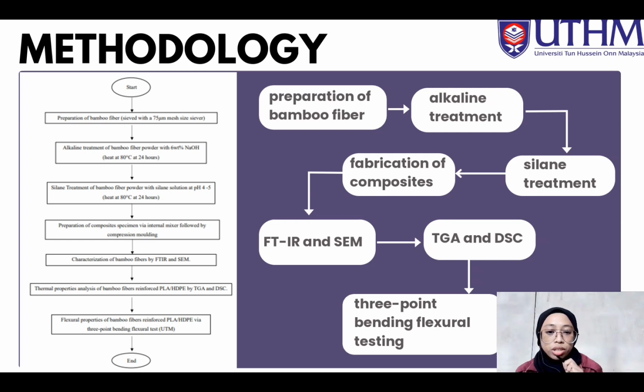And next is about methodology. First of all, we will prepare bamboo fiber, which we will get from a bamboo fiber company, and then we will use that bamboo fiber to do this research. First, we will treat the bamboo fiber with alkaline treatment and silane treatment. For the alkaline treatment, we use NaOH, sodium hydroxide solution, to remove the hydroxyl group in the bamboo fiber.